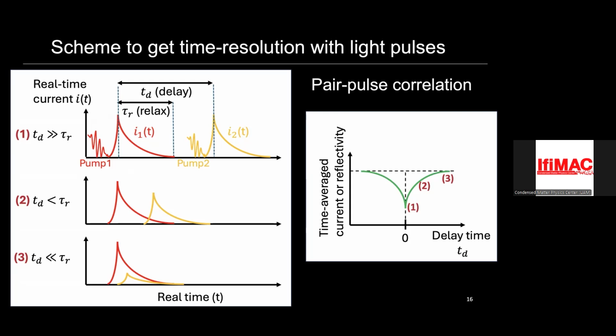The tunnel current that we're measuring is just an average tunnel current. And we measure this average tunnel current as a function of the distance between these two pulses. And that's basically how we do our experiment. Okay. So if you think about what you expect to see, let's say this is the response. When these two pulses are far away, everything just adds together, right? And so you get some response in your system.